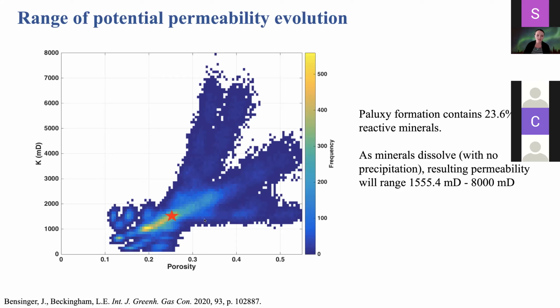So basically we've taken the results from all of our simulations and are showing them here. And you can see as minerals start to dissolve and porosity increases, you have a large potential range of resulting permeability. So anything from about 1,500 to 8,000 millidarcies. Precipitation, on the other hand, there's less variability, but still a pretty wide range of potential resulting permeability that could happen as precipitation occurs. And the other thing I should mention is that just because you have reactions happening uniformly in one place, they could still occur non-uniformly someplace else.